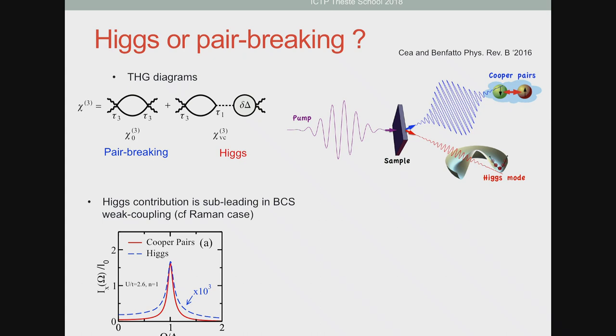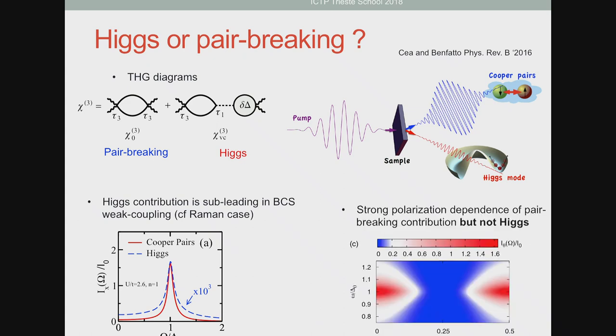Now the bad part of it is that both contributions are resonant at delta, 2 delta, 3 delta, of course, because we know from Raman that we have to have a mode at 2 delta. Both of them are resonant at the same frequency, but one of them is at least 3 orders of magnitude smaller, so this Higgs contribution is generically much smaller in the BCS approximation than this one. Now, there is one way to distinguish between the two, which is in the polarization dependence.